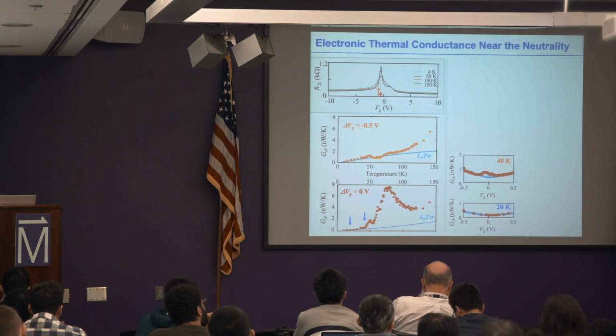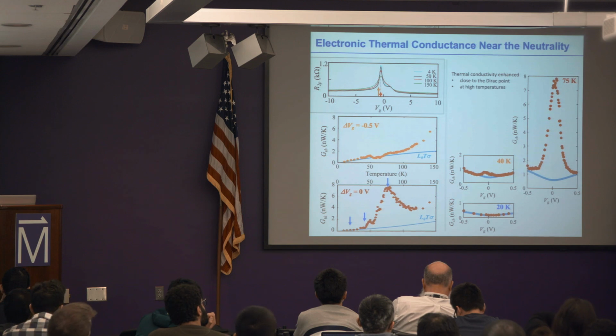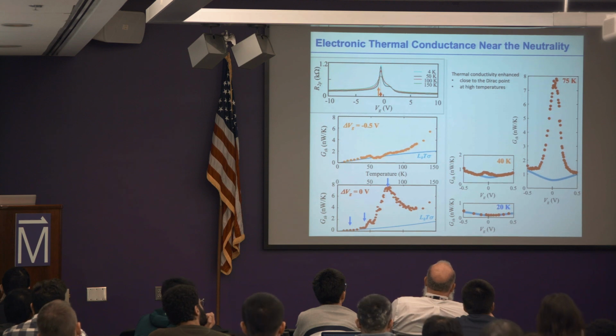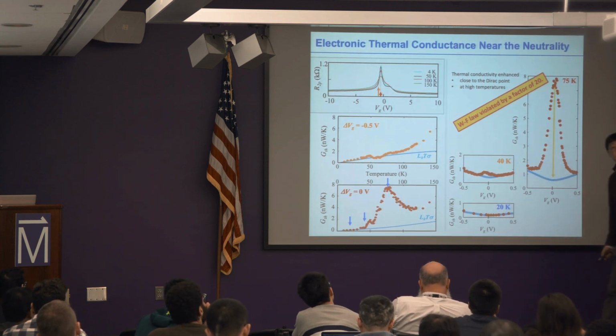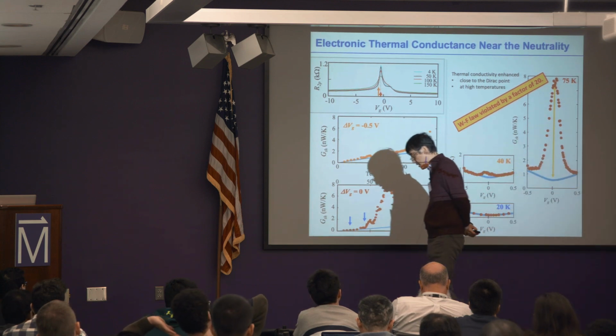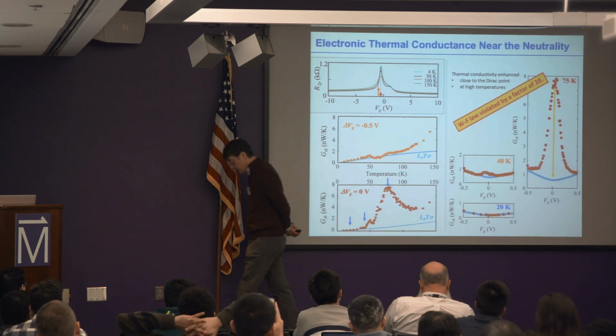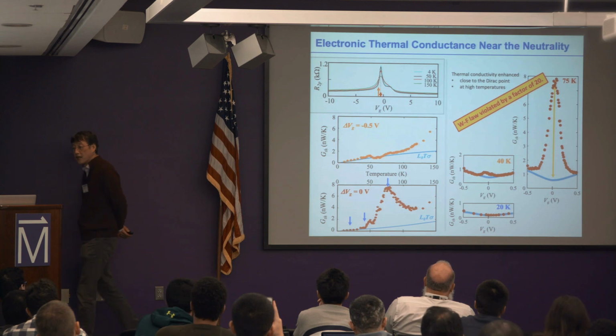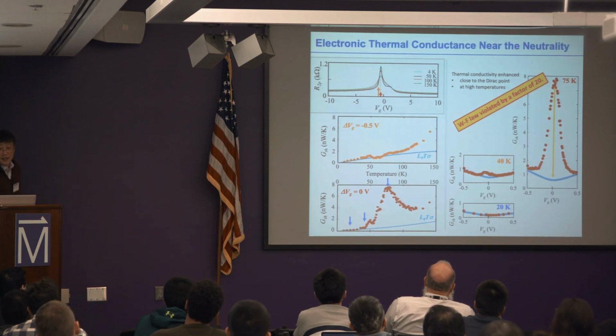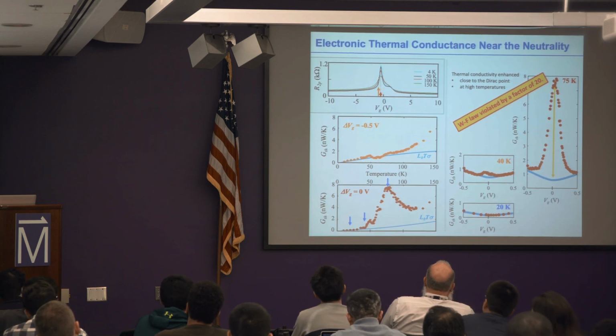Around 75 Kelvin, it's undoubtedly clear that the Wiedemann-Franz law strongly breaks down right at the Dirac point. And this breakdown is about a factor of 20. It's a huge deviation that we see in this sample. So there must be some description that should be in there, right? Okay, so what is happening here?